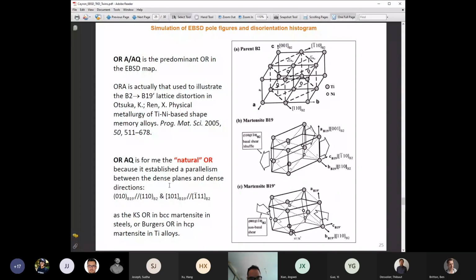AQ is in red. To me it was a natural orientation because it establishes a parallelism between the dense planes and dense directions of the daughter and parent phases. It's exactly as the Kurdyumov-Sachs orientation in steels. Kurdyumov-Sachs established a parallelism between the dense plane and dense direction. So here it was the same. So even if we have many orientation relationships, this orientation AQ is special to me.